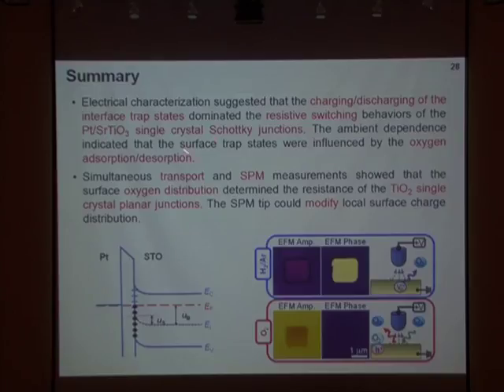In the first part, I mainly talk about the Pt/SrTiO3 single-crystalline junctions, and I believe that the charging and discharging of interface traps is really important. These trap states are affected by oxygen adsorption, so ambient effects are really important.